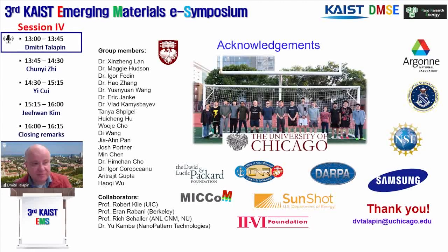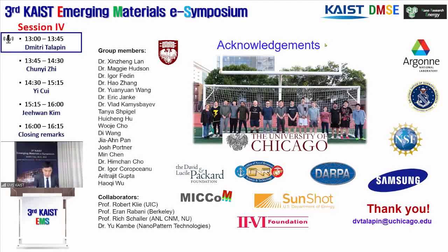And overall, of course, there will be some variation. I don't want to say that we have exactly the same composition. So there will be a little variation, but surprisingly, it works quite well. So the ensemble line width of these colloids is not bad. It's slightly inferior to the best indium phosphide samples, but not much. Okay. All right, thank you.